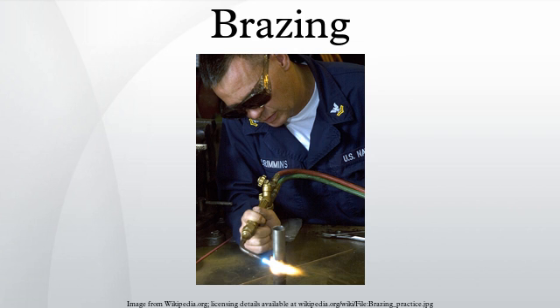Excess flux should be removed when the cycle is completed because flux left in the joint can lead to corrosion, impede joint inspection, and prevent further surface finishing operations. Phosphorus-containing brazing alloys can be self-fluxing when joining copper to copper.